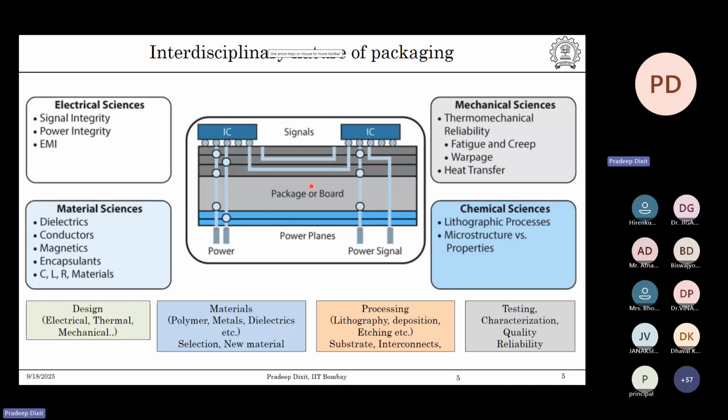If you look at this particular package here, this could be a printed circuit board, or for example a silicon material. It could be glass-based material, alumina-based material, and so on. These materials are typically brittle in nature. Most of the ceramics here are all going to be brittle. The dark side, the black color which I'm pointing out here, is polymers. Their objective is to provide electrical isolation. And this blue line here is what we call an interconnection line, and it is typically made out of metal. So for all these advanced semiconductor packages, if you want to make a reliable part, we have to worry not only about the metals but also polymers. Similarly, these solder joints are typically an alloy. Most of the time we are using tin-based material and so on.